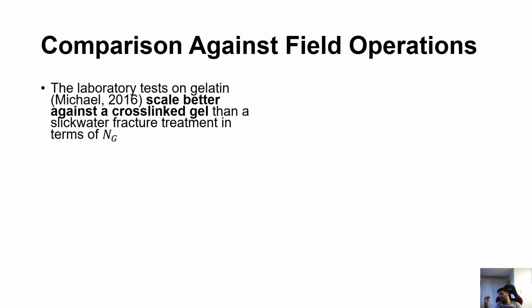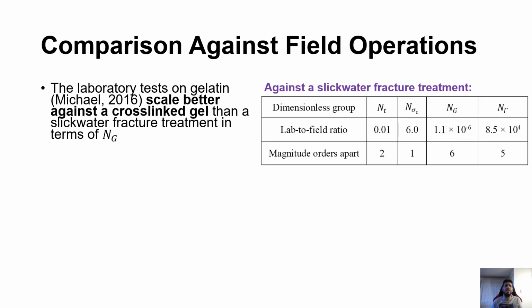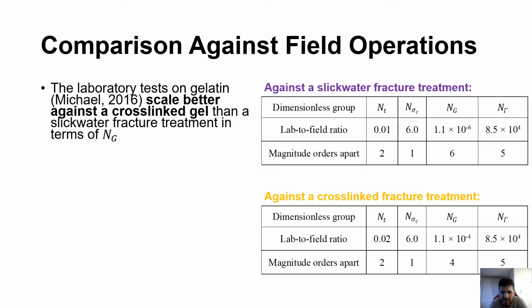Now I took the parameters from my master's experiments and I compared them against typical field operation parameters from a slickwater fracture treatment and a crosslink gel fracture treatment from the Barnett shale, and we found that the crosslink gel treatment scales better against my master's experiments compared to the slickwater fracture treatment. And we see here the magnitude orders apart for each dimensionless group for the slickwater and the crosslink gel.